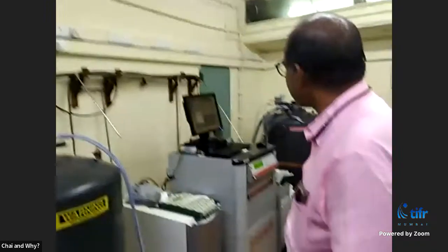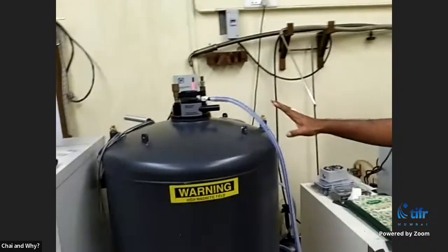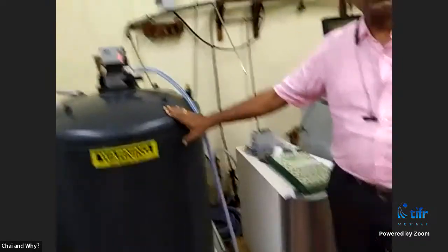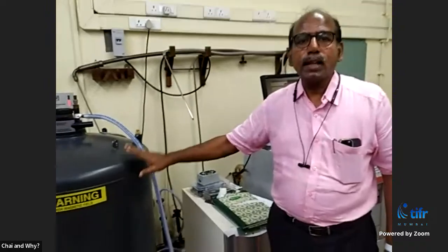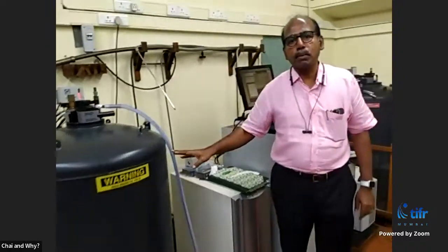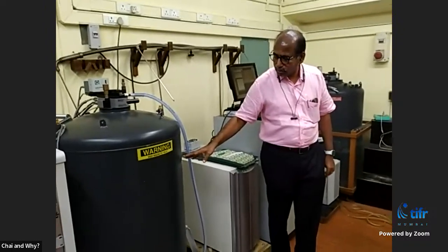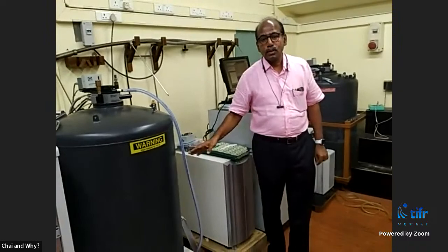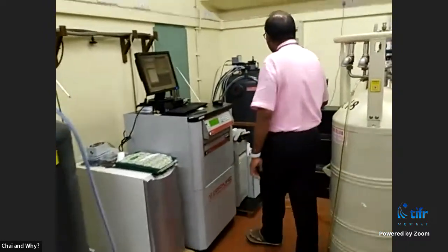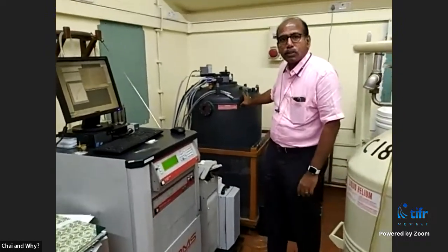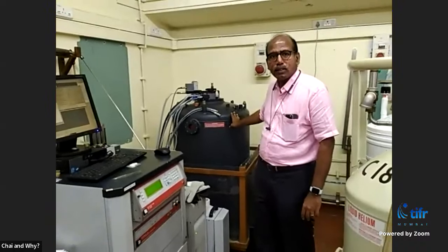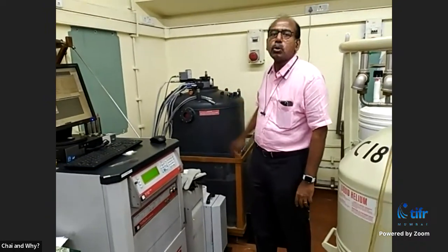Suppose the sample is superconducting, we can see a zero resistance. If the sample has a magnetic ordering, we can see the magnetic transition at some low temperature. So here, these are 2 different instruments. This is again a cryostat, which contains liquid nitrogen and liquid helium. Inside this, we have a superconducting magnet, which can go up to 9 Tesla of magnetic field, 90,000 Gauss. And here we have a 14 Tesla magnet, 140,000 Gauss of magnetic field is possible in this instrument, and we can go down to 2 Kelvin and do the electrical resistivity measurement on this sample.